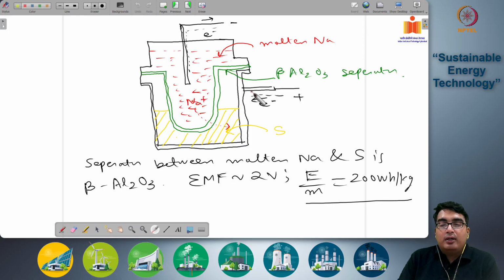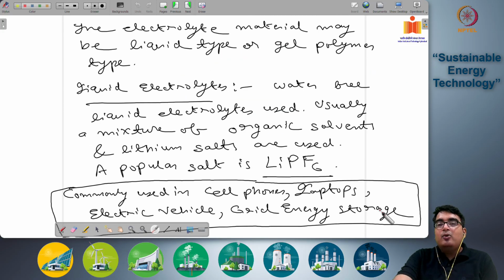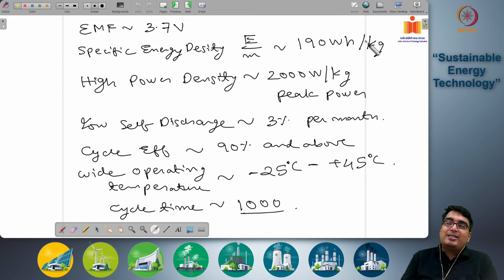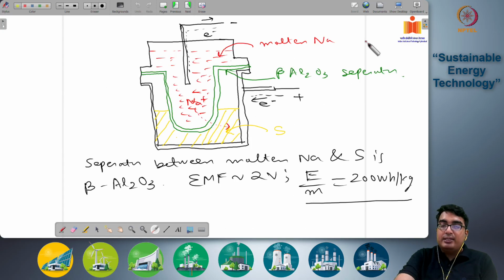Okay, and you have two electrical contacts contacting the sulfur container here and the sodium container here. Electrons are coming out of the sodium, going to the external circuit and coming back and reaching the sulfur through this electrical contact here. Okay. The EMF available is around 2 volts, relatively good, and the specific energy density is 200 watt-hour per kg, which is almost as good, if not better than that of a lithium ion battery. So you have very good energy densities even though the EMF is low. Okay.